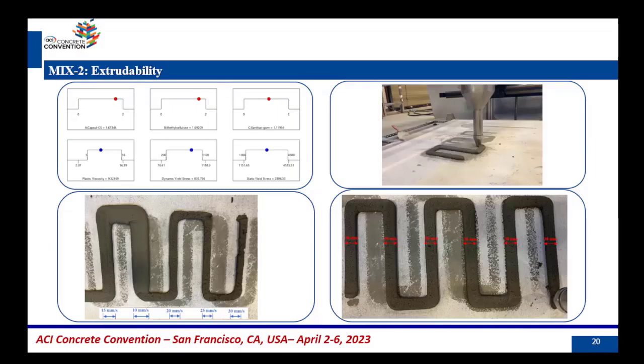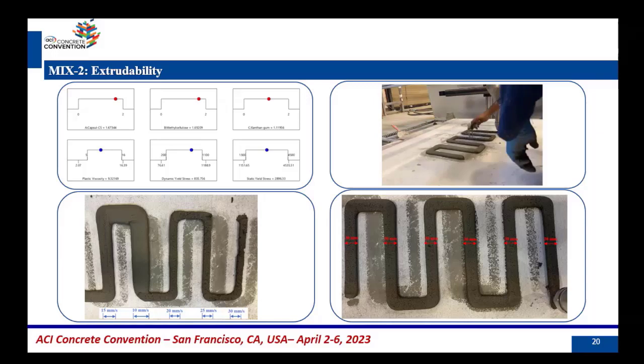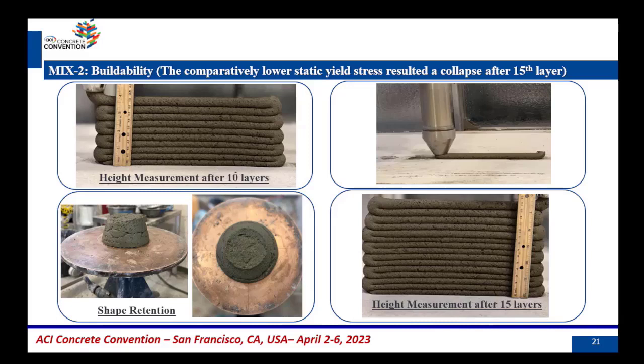Similarly, for mix 2, which has different content of factors A, B, and C, again the printing speed for this case was 15 millimeter per second, and we get a good dimension consistency and conformity in this mix too. And again, in terms of buildability and shape retention, you can see the shape retention is quite good in this case. But for buildability, this mix collapsed after 15 layers. The reason behind this is the static yield stress of this mix was comparatively low as compared to the other 4 mixes, so this mix collapsed early.